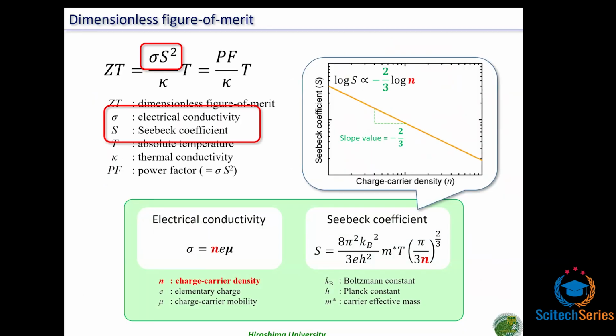It is already known that the electrical conductivity is expressed by the product of densities and mobilities of charge carriers. So in order to enhance the electrical conductivity, increasing the density or mobility of charge carrier is crucial. When it comes to the Seebeck coefficient, such an equation has been already proposed for inorganic thermoelectric materials, and it can predict a straight line in a log plot of the Seebeck coefficient against charge carrier density. However, such a correlation has not been proposed for the organic thermoelectric materials because of their short history.